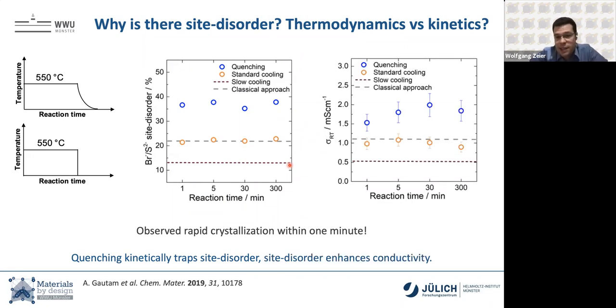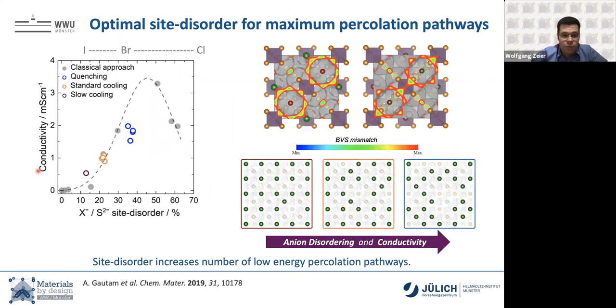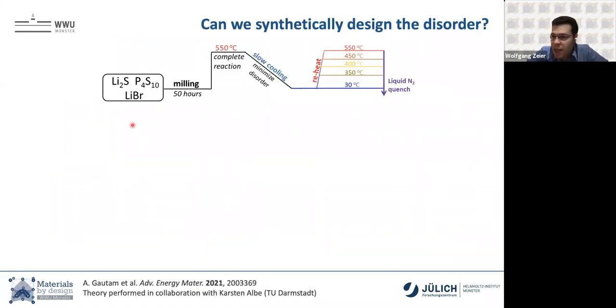So slow cooling makes it order into its thermodynamic phase, the thermodynamic ordering that it actually wants to be in, or at least as close as possible. And we do see that there's a direct correlation between this disorder and the conductivity. The quenched materials with the higher disorder have a higher conductivity. So if we go back to this initial plot, if you quench them, you get higher disorders, you get higher conductivities. Now we thought about, okay, let's see how much we can push this thought of synthesis matters here. So instead of quenching them after different times at 550 Celsius, we decided to quench them at different temperatures.